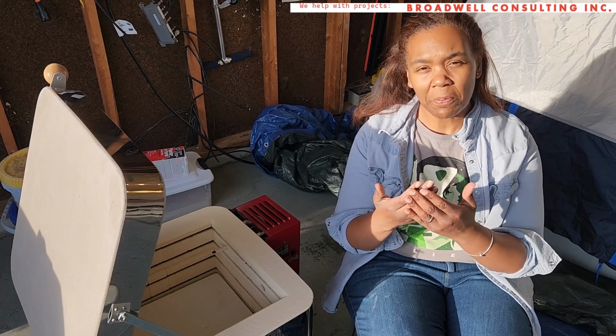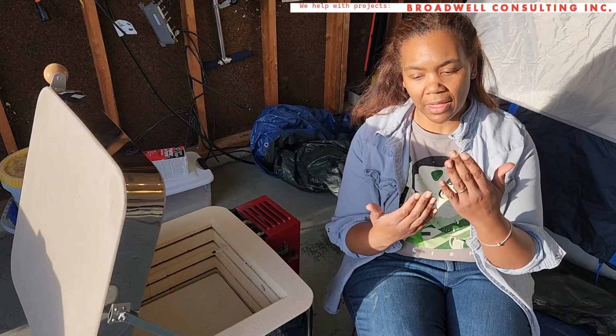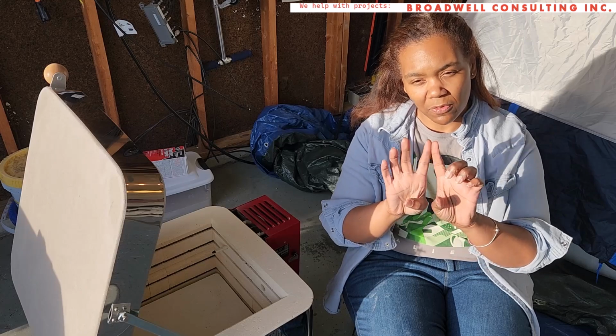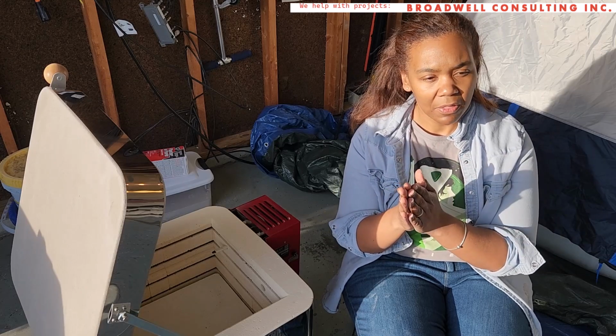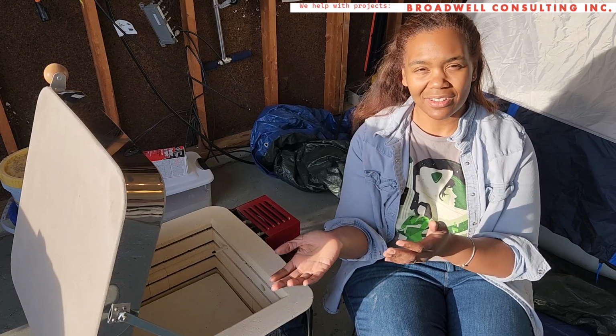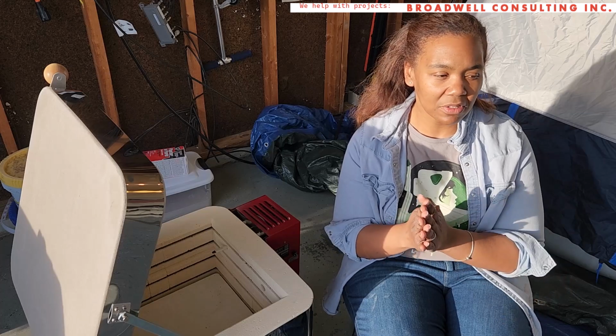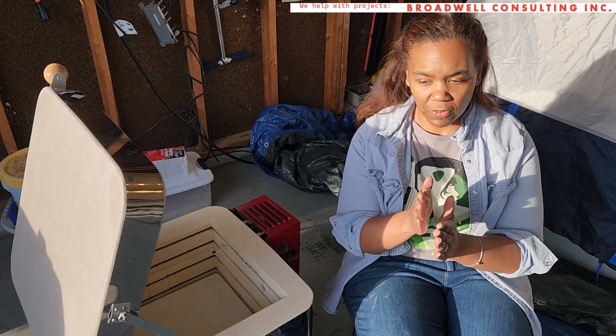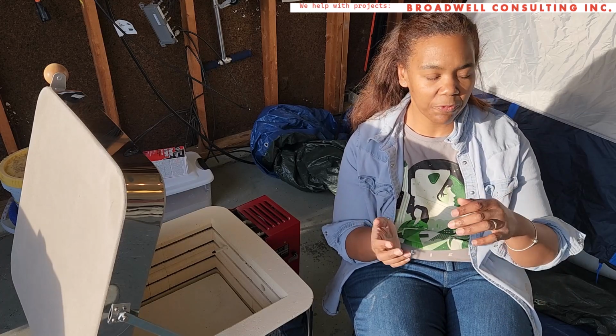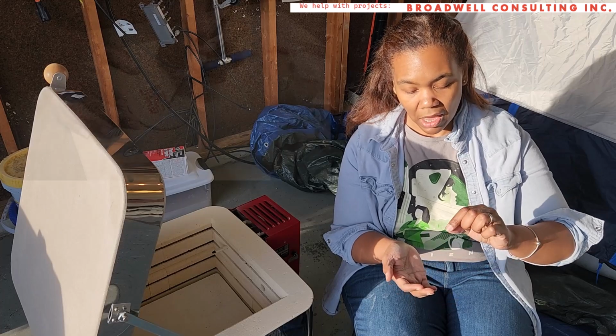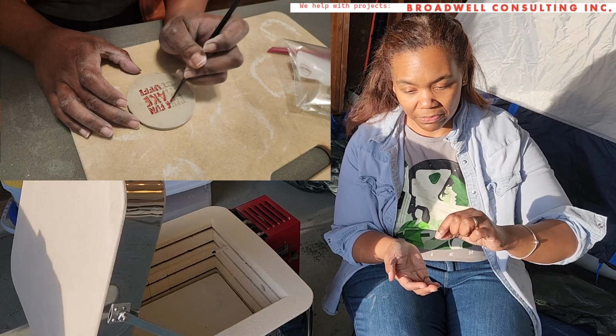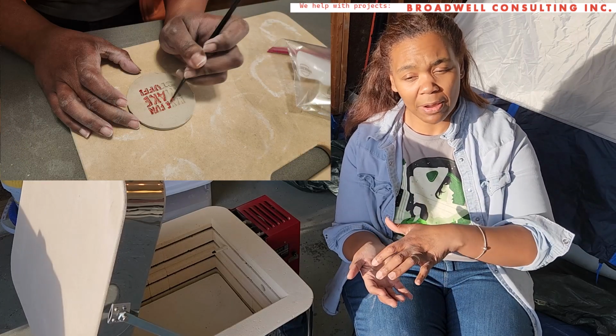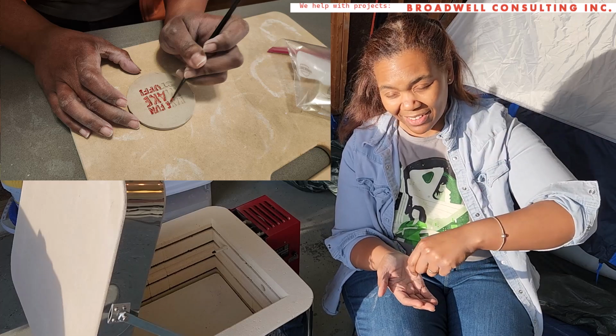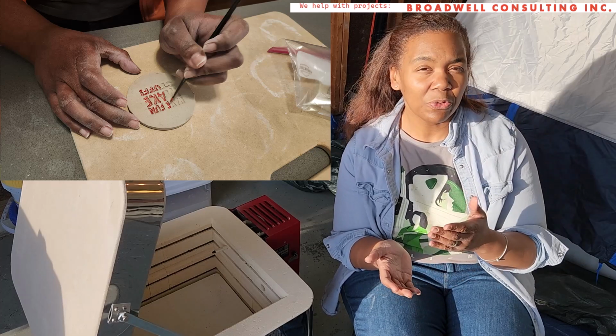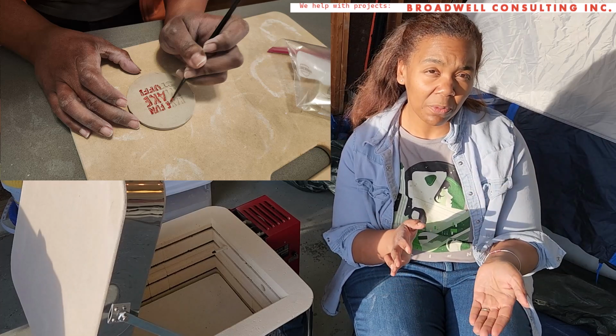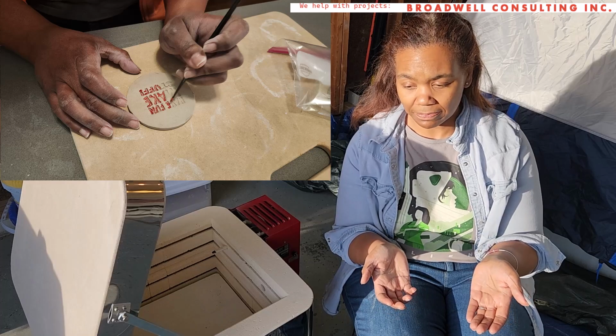If there's fit problems between the ceramic and the glaze, sometimes you'll see very fine cracks that happen in the glaze. I use Kentucky Mud Works clay, and then I also use Kentucky Mud Works clear glaze so that they have a good fit. I neglected to say, for the inside stamp of the mug, I painted the Have Fun Make Stuff before I bisque fired it, because otherwise I wouldn't have been able to get down to the bottom of the mug. You can apply underglaze either before bisque firing or after bisque firing.